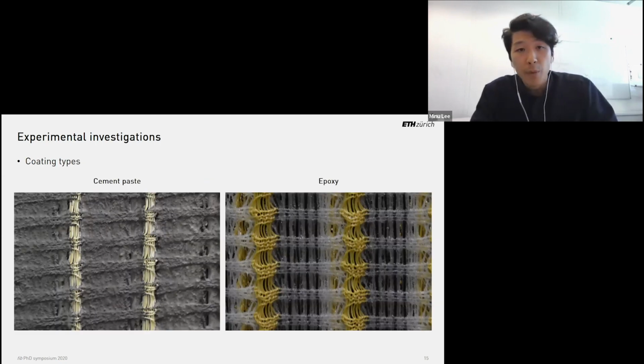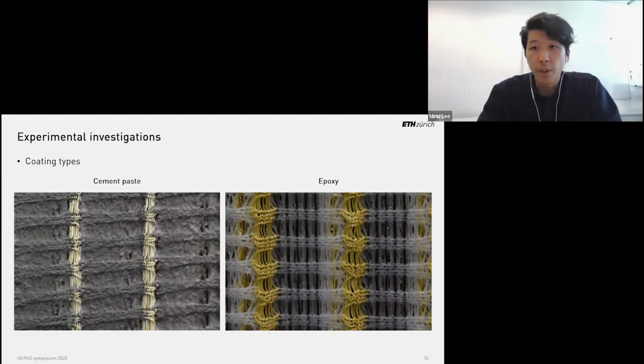Okay, to eventually work as a formwork and reinforcement system, the textile has to be coated to create a closed surface where the concrete can be poured onto. We had a look at 2 different coating types, one being a fast-setting, highly fluid cement paste, which had been used in the initial applications of the knitted technology, and on the other hand, a low viscous epoxy resin, which is more commonly used as impregnation of conventional textile reinforcement.